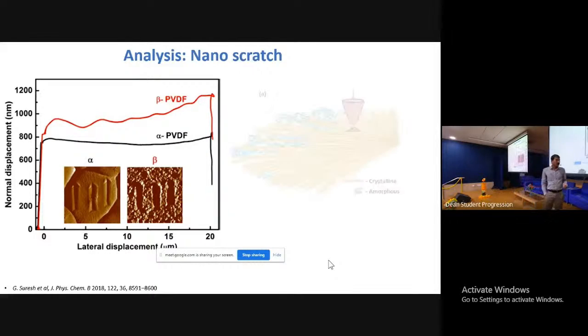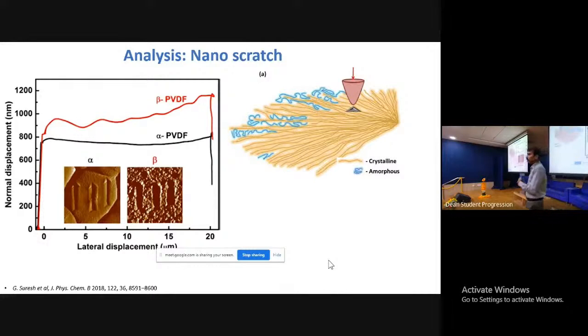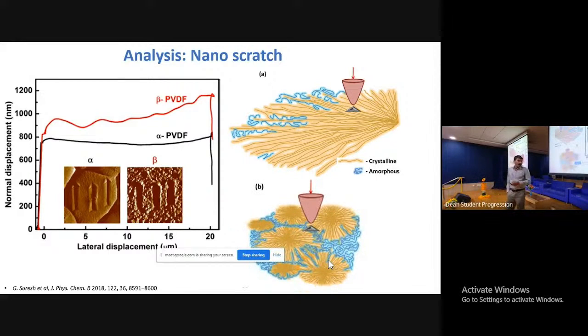And why it is so can be explained. We tried to understand why it is happening. In the alpha phase, these bigger structures or microstructures are called spherulites, a physical structure where polymer chains are extended or elongated. In between them, in the interpolymer chains, some amorphous regions are there, which are responsible for the plastic nature of the given material. So if the structure is bigger, when you indent, most of the time it is going to indent over this particular region to get the alpha nature. Whereas if the sample is like the beta phase in this case, the microstructures are very, very small.